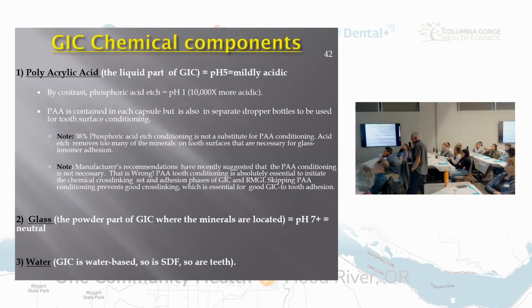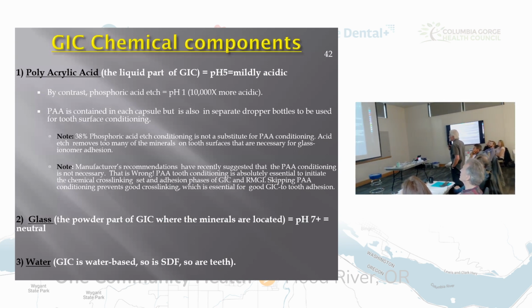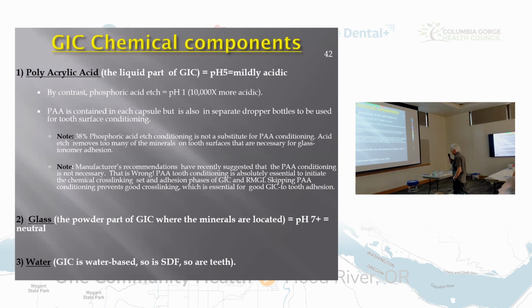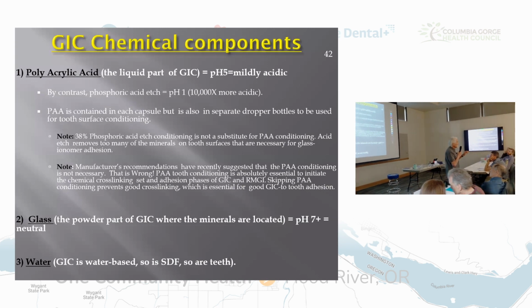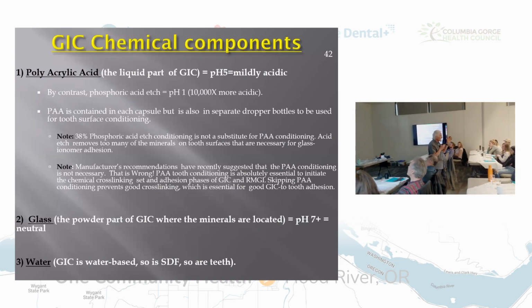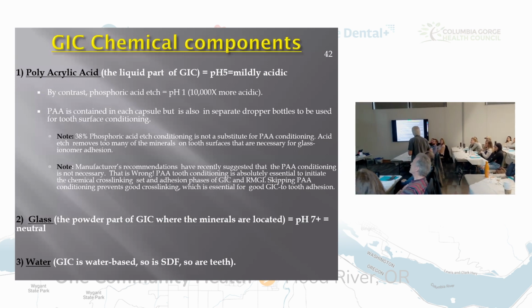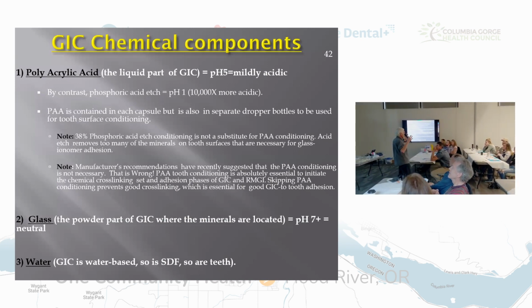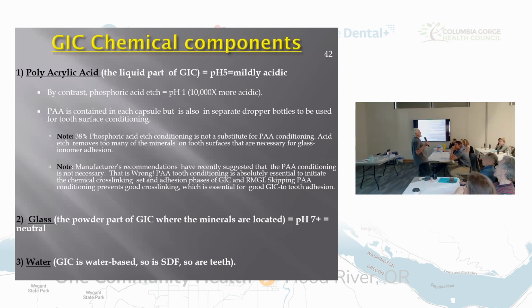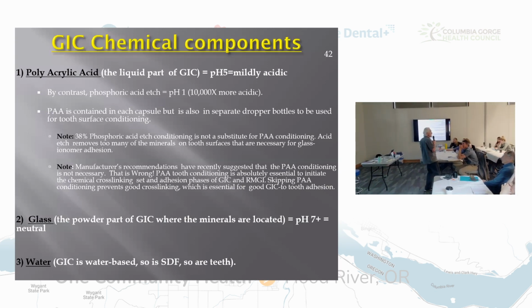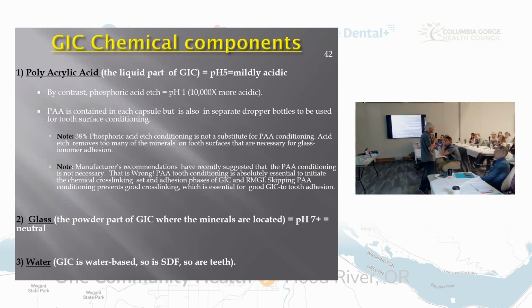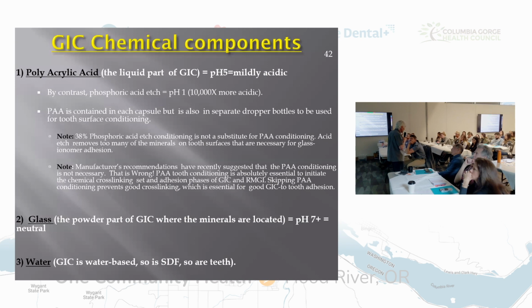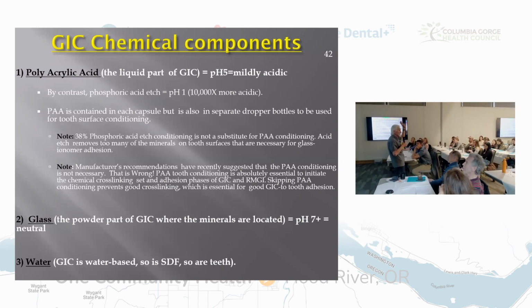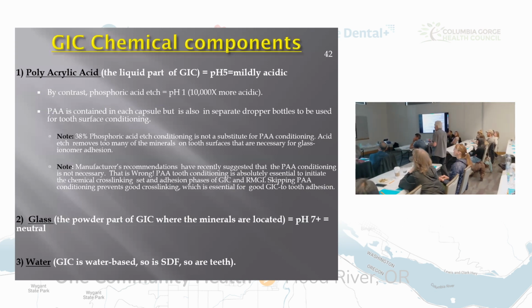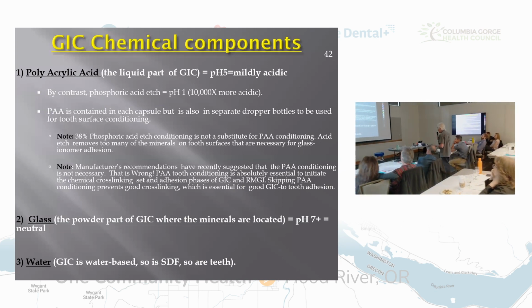Polyacrylic acid is contained in the capsule, but it's also important to use it from a separate dropper bottle to condition the surface of the tooth. Because the mineral ions on the surface of the tooth need to be woken up because they're asleep. They're not ready yet. You wake them up with polyacrylic acid. You don't want to wash them off. If you put phosphoric acid on there and you leave it on long enough, you're just going to rinse them away. They're going to go up into the high-speed suction. Quit with that phosphoric acid stuff.